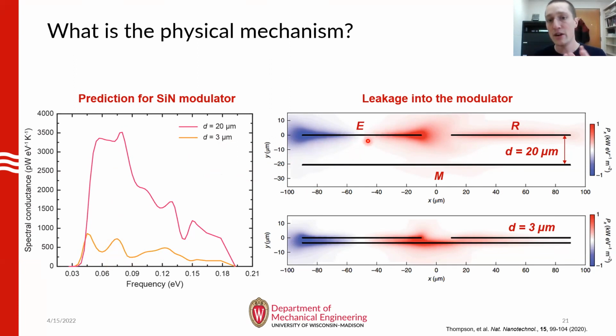In this case, we introduce thermal sources of radiation onto the emitter, so it starts emitting. Here, the red color corresponds to the Poynting flux in the plus X direction, and the blue coloration corresponds to Poynting flux in the minus X direction. With a large vertical offset of 20 micron, the Poynting flux occurs largely in plane, and a large fraction of the energy from the emitter is transferred to the receiver.